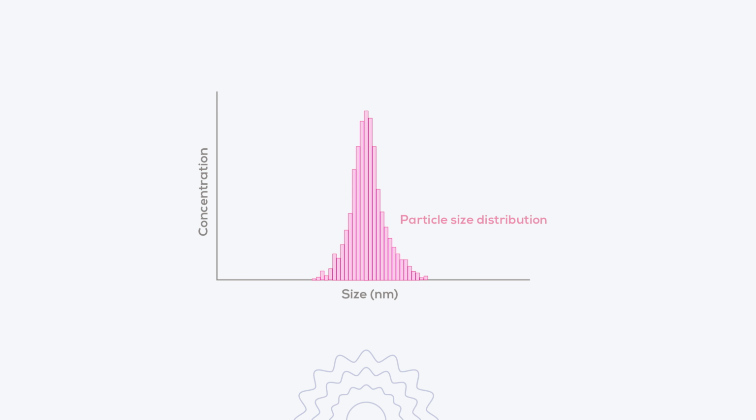In nanomedicine, particle size is expressed in three main ways. The first is to give the mean or mode particle size with an appropriate measure of error. The choice of mean or mode depends on whether your particles are normally distributed. If they are, this indicates that the mean should be used. And if the distribution is skewed, the mode is more appropriate. So far, so easy. The second method is to look at the distribution of the particles within your sample as